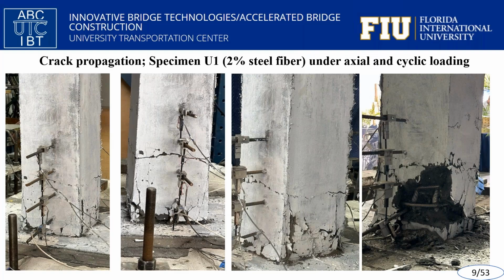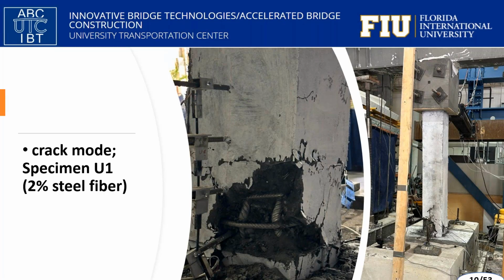Here you can see the crack propagation of our first specimen, which had 2% steel fiber. Fracture cracks appear near the base of the column at early loading stage. Cracks were concentrated at the bottom, aligning with the area of maximum bending moment and shear. As the load increased, flexural and shear cracks extended upward. This figure shows the final stage of loading, which means the column experienced about 7-inch lateral displacement.